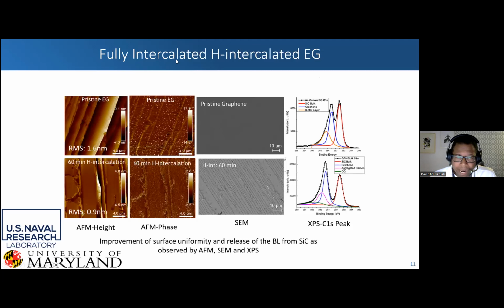We can look here at AFM. We have our surface roughness, we have our phase, and we have SEM images as well as XPS, and everything points to improved surface uniformity. This change in contrast in our SEM lets us know that we've released from the silicon carbide, and we're actually getting some charging, because we don't have the insulating silicon carbide to soak everything up. And we get the splitting of our C1s peaks, showing that instead of having this buffer layer, and the distance between our graphene peak and our silicon carbide bulk, we remove our buffer layer peak as a result.